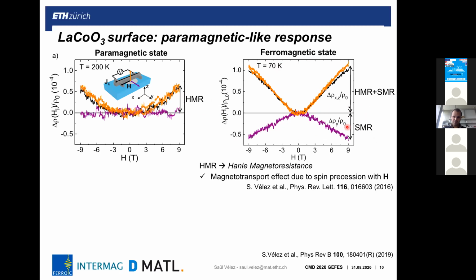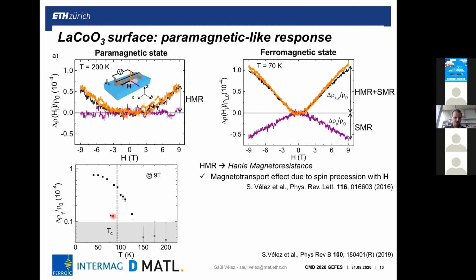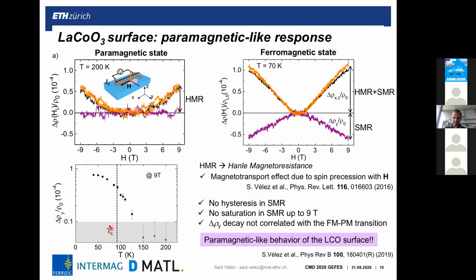So there should be some magnetic moments aligning towards this direction, and there is some change with respect to zero field. But importantly, we don't see a saturation up to 9 Teslas, telling us that there is no correlation between the bulk properties of this film and what we measure at the surface. So we tracked this amplitude as a function of temperature. We see that there is no correlation with the transition temperature of the film, and we see that this surface behaves as a paramagnetic-like surface.